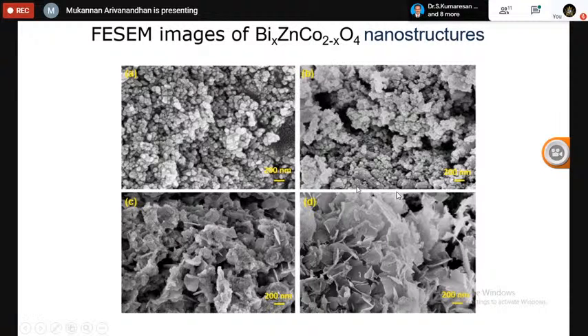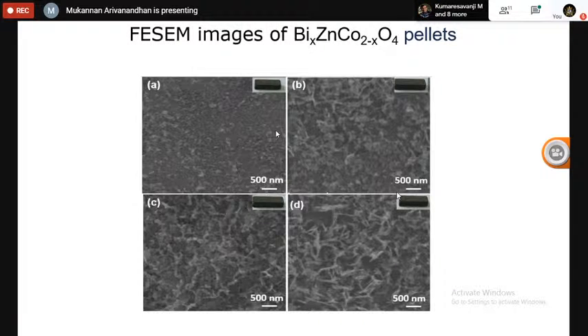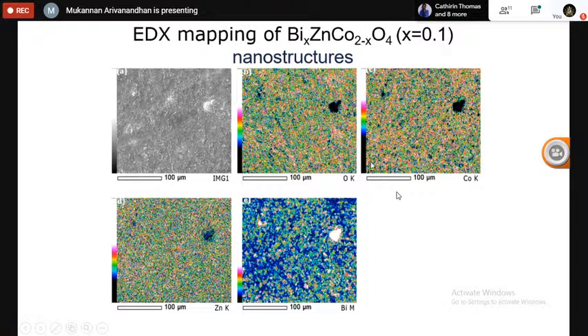These are the morphological features of the sample, and the morphology systematically changed from spherical to sheet-like structure as the bismuth content increased in the system. And this is the morphology of the pelletized nanostructure. That means even after pelletization and sintering at high temperature, we checked how the morphology changes. The morphology has been retained even after sintering at high temperature, with the same particle and sheet-like structure. And this is the EDX analysis of the sample. The EDX mapping shows that each and every constituent element is homogeneously distributed.